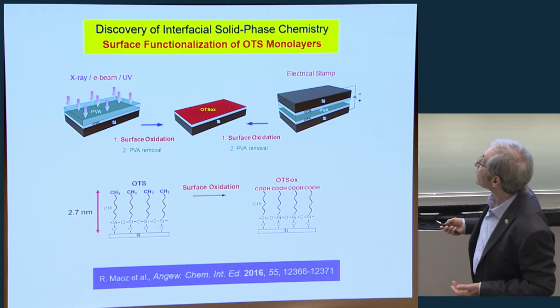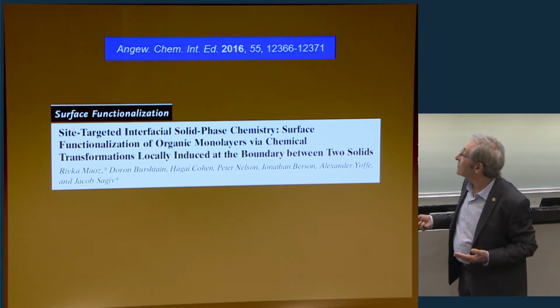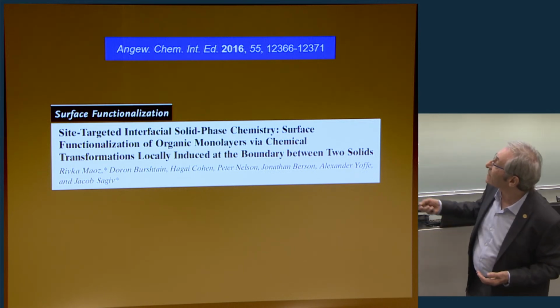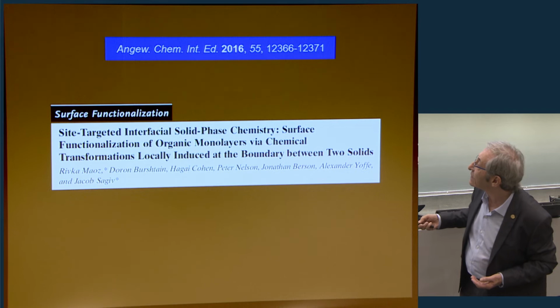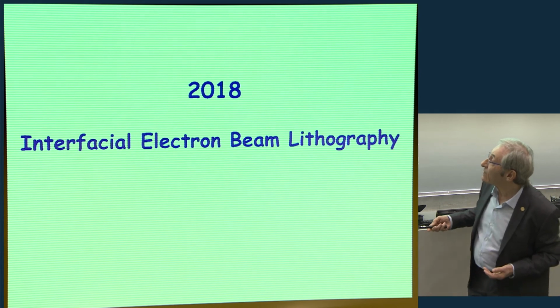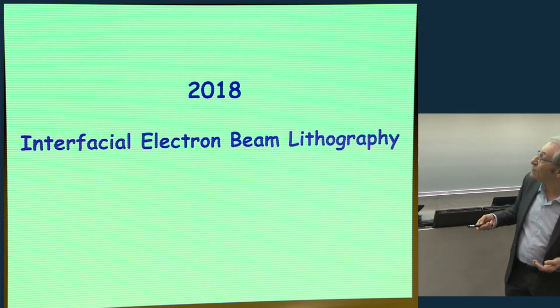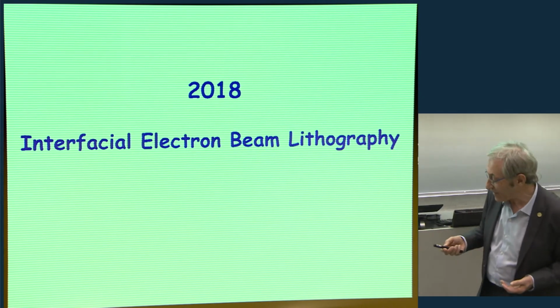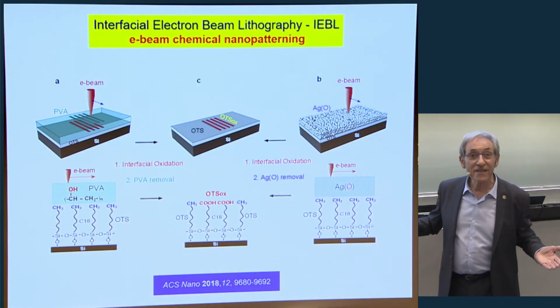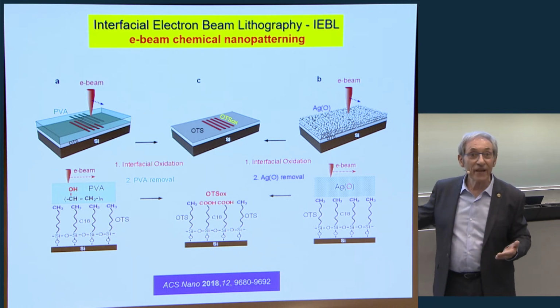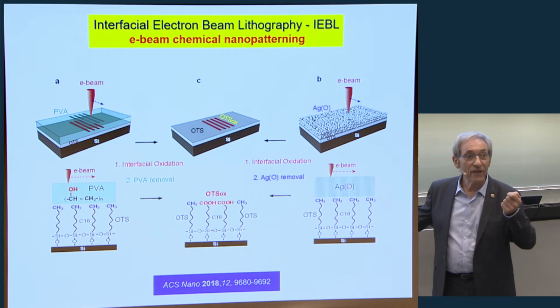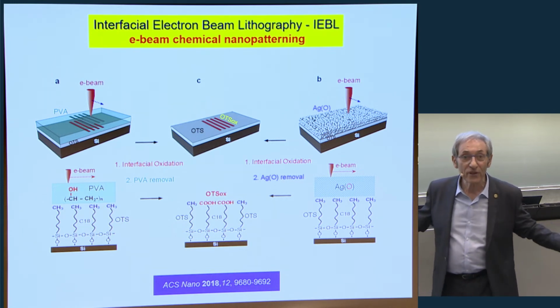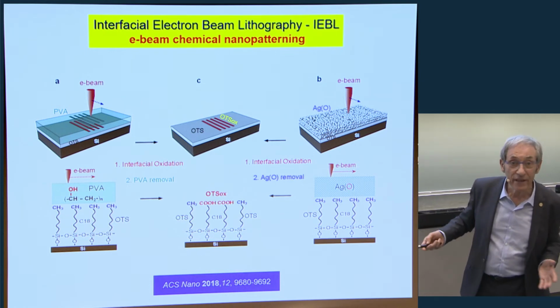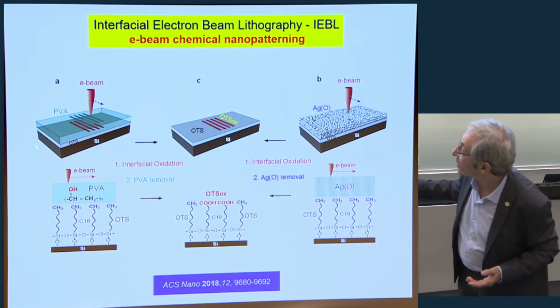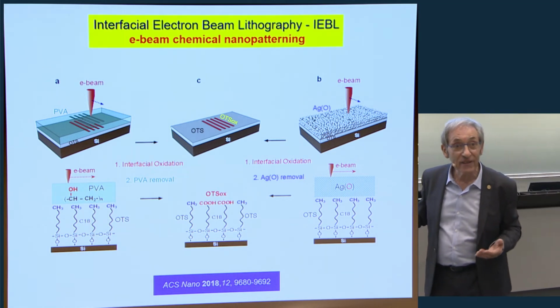Okay. So once we knew that this can happen, and this was published in Angewandte Chemie, you can see it, on this basis we invented what we refer to as interfacial electron beam lithography. We are now in 2018. So this is exactly the same process now on the nanoscale. We can use the electron beam of an electron beam writer, which is used in electron beam lithography with resist, but in a different way. Here, the polymer is not a resist. It's a reagent and a catalyst.